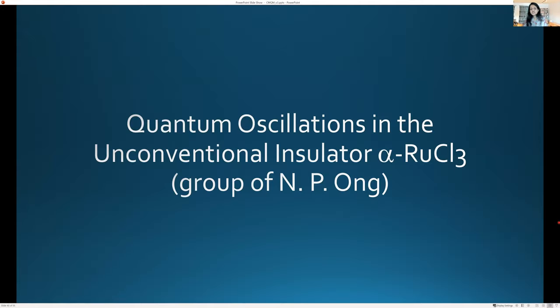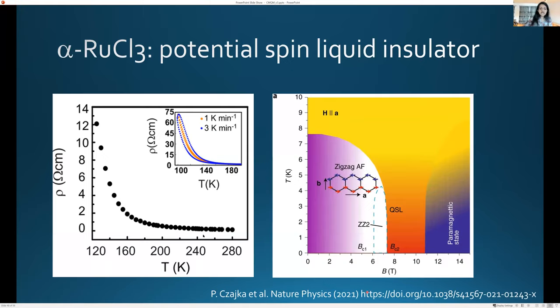So very recently, the group of N. P. Ong has reported bulk quantum oscillations in another unconventional insulator, alpha ruthenium trichloride. And again, with all these different classes of materials, you can have many different types of materials and behaviors within this class of material. And it seems as though maybe there are different types of Fermi surfaces in each of these materials. And so in this case, again, you see good electrical insulating behavior. This material has been studied for quite a while.